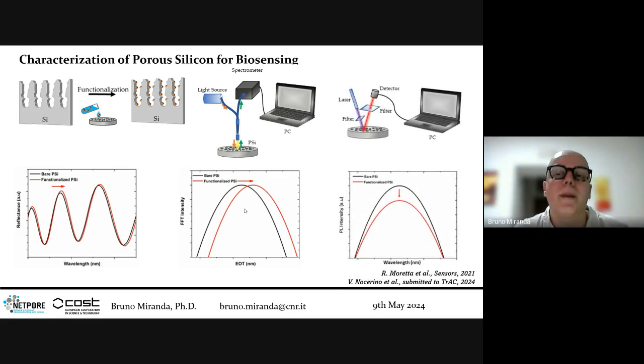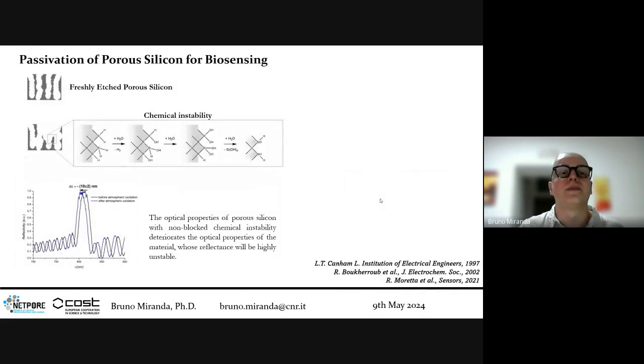But we can also make photoluminescence analysis. So you have a UV laser, and it is photoluminescent. Generally, when we functionalize photoluminescent porous silicon, we have a decrease in the photoluminescence that is due to the quenching effect caused by the presence of molecules.